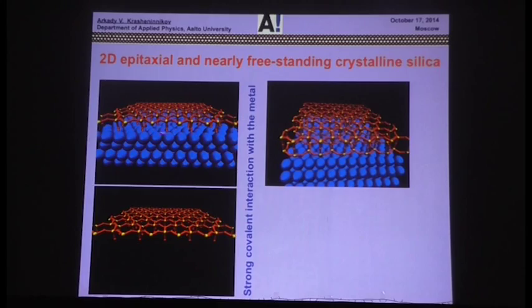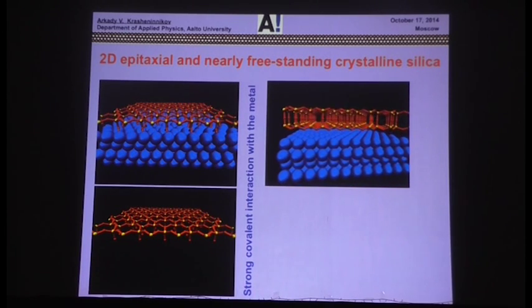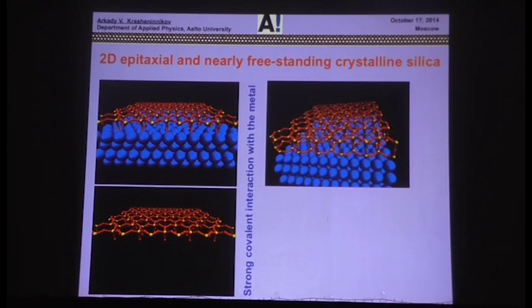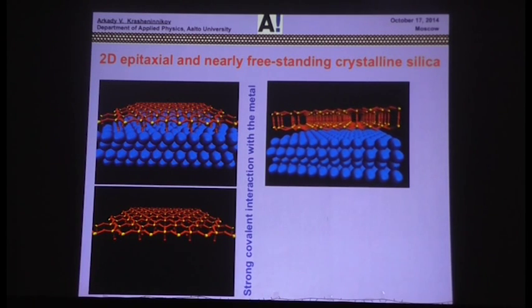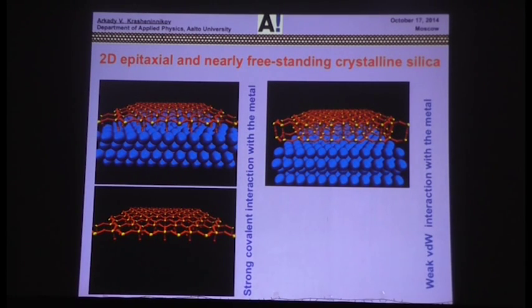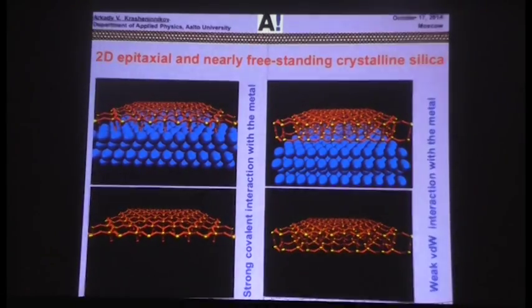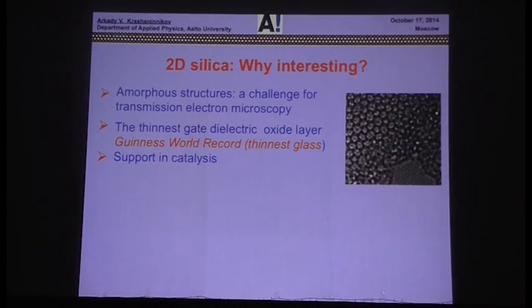And this structure doesn't exist without the metal substrate, like silicene, more or less. And this is silica bilayer, which is van der Waals bonded and it can be removed from the metal. So why interesting? This, by the way, is now in the Guinness World Records book as the thinnest glass, but seriously speaking, it's a very interesting support and challenge for microscopists.